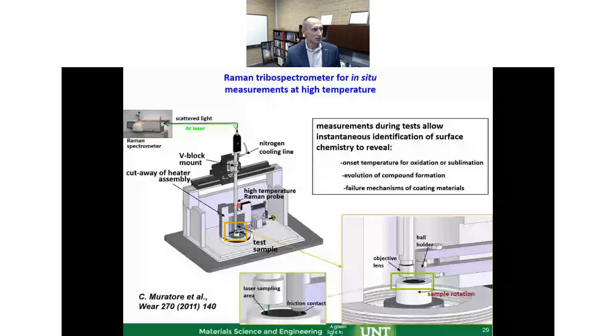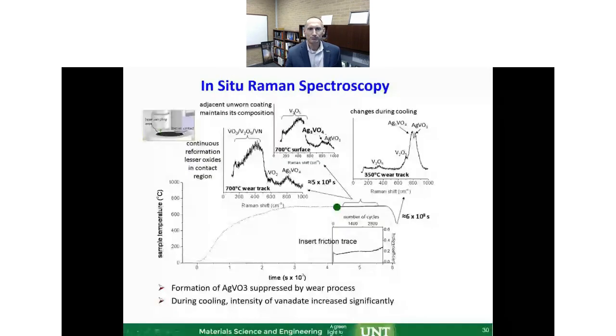You're talking about 1,000 degrees C here, and bringing the probe all the way in, keeping it optically intact, meaning no distortion when you're ramping the temperature up and down, taking the signal out of the fiber optic to the Renishaw Raman. Now we have the option to track as we spin, so we don't stop the spinning, and as we heat, we don't stop the heating either. So with this, we can look at what type of oxide we're forming on our surfaces. To my knowledge, this is the only apparatus of this type that was constructed. It is now rebuilt at the University of North Texas. We're using it. I'll show you some other examples.